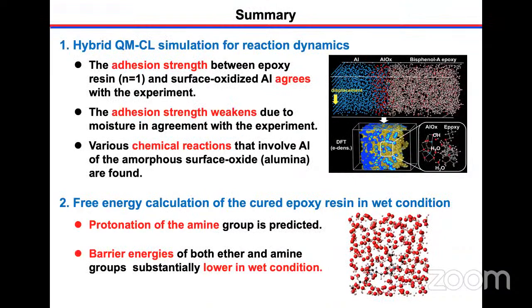So this is a summary of our present study. For the first part, we have performed the hybrid QM/CL simulation of the reaction dynamics. Then we found that the adhesion strength between the epoxy resin and the surface oxide aluminum agrees with the experiment. And also the adhesion strength weakens due to the moisture, in agreement with the experiment. Additionally, we found various kinds of chemical reactions that involve the aluminum atoms of the aluminum surface oxide and epoxy molecules.